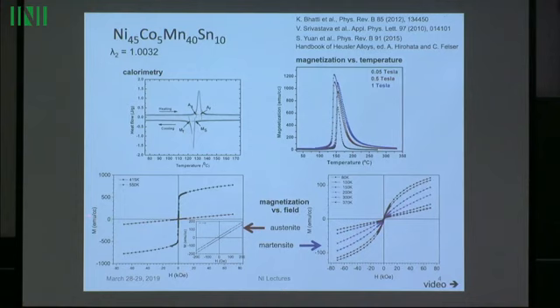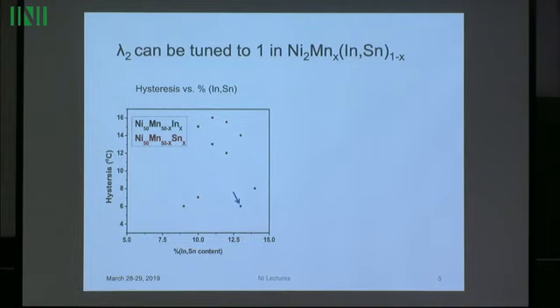As I mentioned, this is again a whole series of open questions. You could think that if your free energy not only depends on deformation gradient, but also depends on magnetization, then the whole thing about lambda 2 = 1 and supercompatibility and low hysteresis goes out the window, because this material is magnetic. It has magnetic energies, there are divergence-free conditions on magnetization, and so forth. We don't know anything about that, basically. But the observation is that it matters very little that you also have magnetization. One would think it should matter. From a theoretical point of view, the energies are quite large, but it seems that the compatibility conditions, ignoring magnetism altogether, are still relevant for magnetic materials. For example, in this nickel-manganese-indium system, or nickel-manganese-tin, this is a tuning.